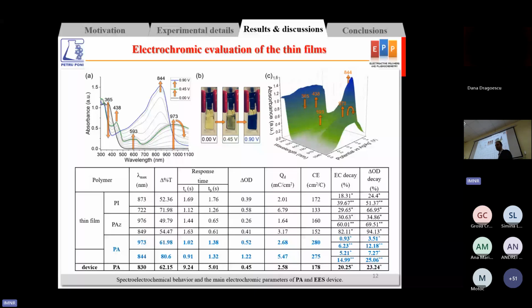Since the polymers change color during each oxidation process, we plan to investigate the spectroelectrochemical aspects. So the polymers deposited on ITO substrates were subjected to various potentials with 50 millivolt increments. As the potential increased, new absorption bands started to appear in the near and visible region of light, and it was associated with the change to green color of the film.